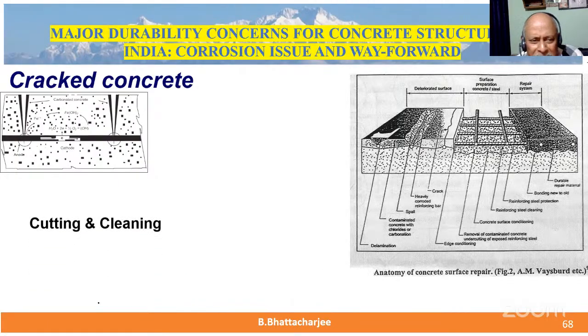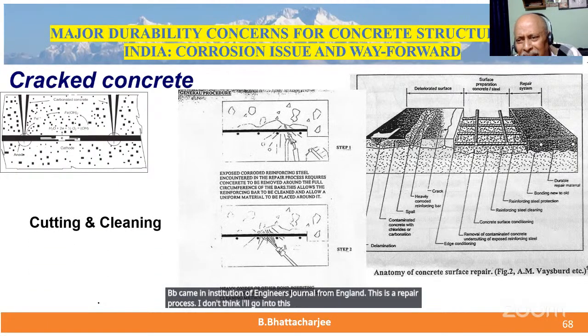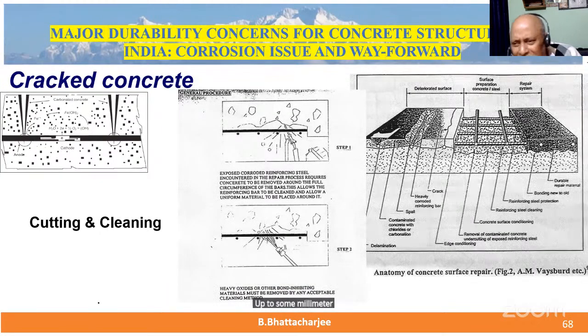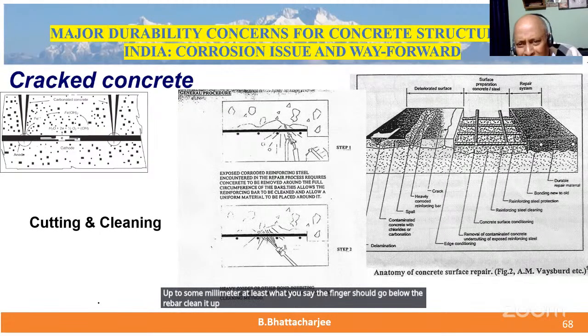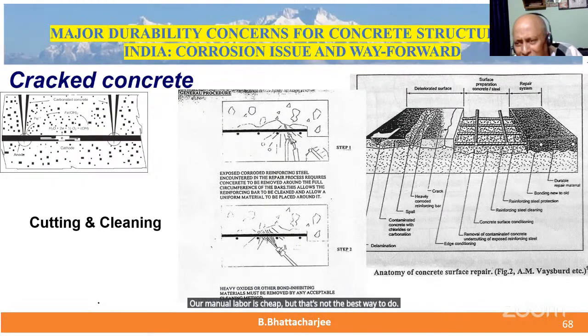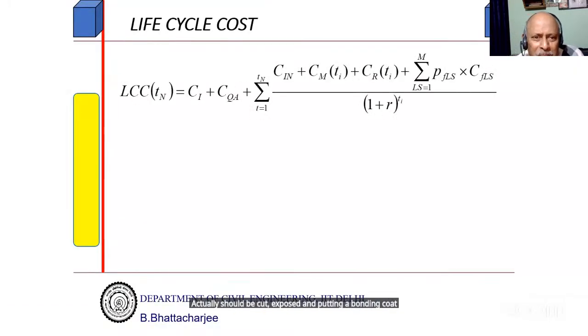This is the repair process. I don't think I'll go into this. Remove concrete up to some millimeters, at least what it says, the finger should go below the rebar, clean it up, and cut it. Nobody is doing cutting in India in this type. What they're doing is hammering and taking, because our manual labor is cheap, but that's not the best way to do it. Actually, it should be cut, exposed, and a bonding coat applied and then repaired with a polymer modified material.